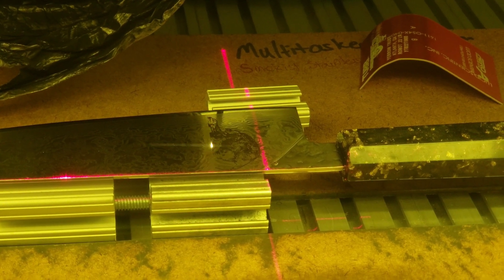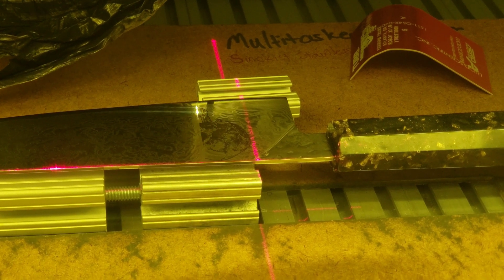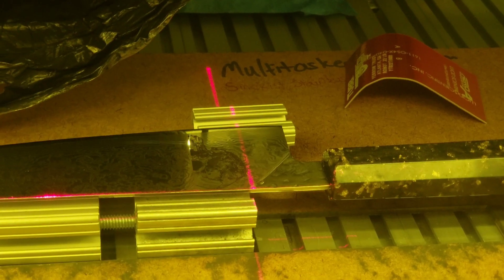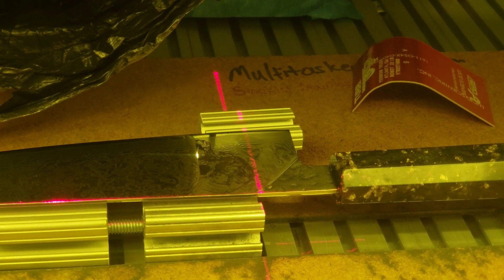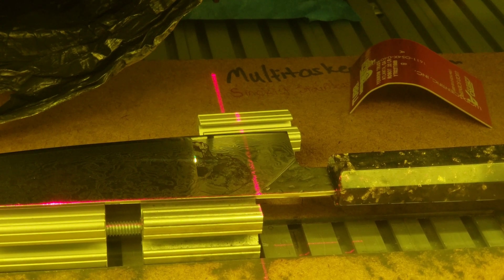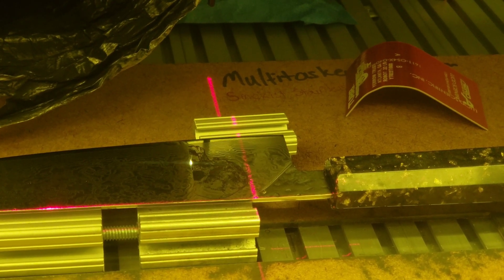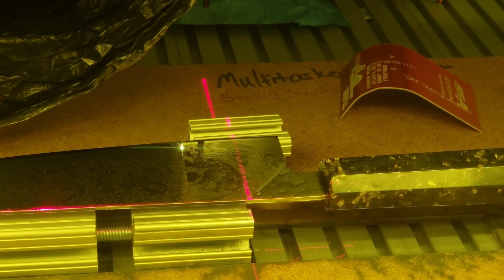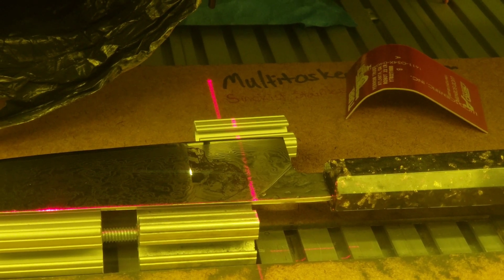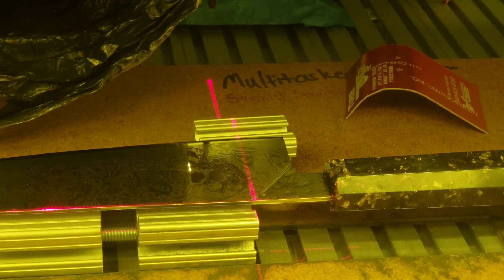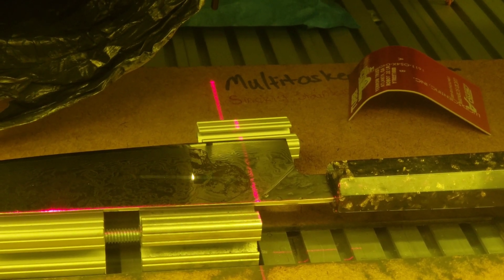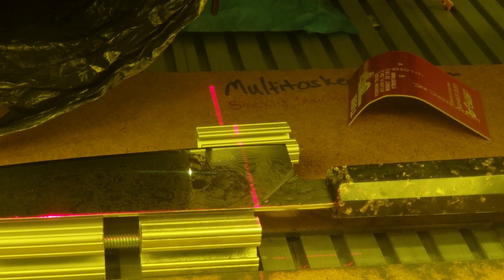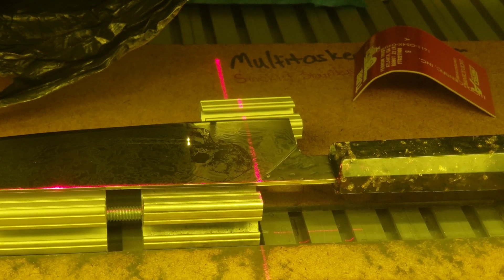Here the engraving is about two-thirds of the way complete, this is real-time speed. The one setting that I didn't talk about so far is the height of the laser beam. The laser is set at about three millimeters above the focal point, the normal focal point. What that does is it makes a little bit wider beam and it doesn't etch as deep into the metal. It doesn't vaporize the metal, instead it does more of a color change to the metal, but like a deep penetrative color change so it doesn't just rub off the surface. You can't even scratch it off or sand it off, it's pretty deep in there. Well, if you sand hard enough anything's going to be removable.